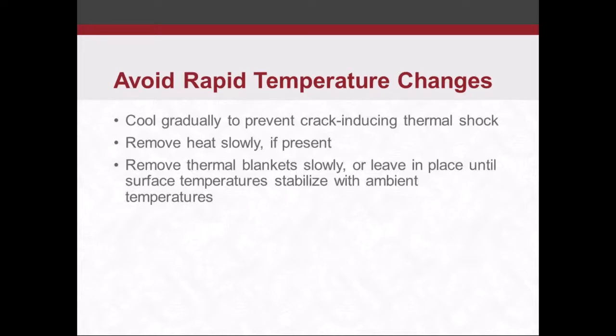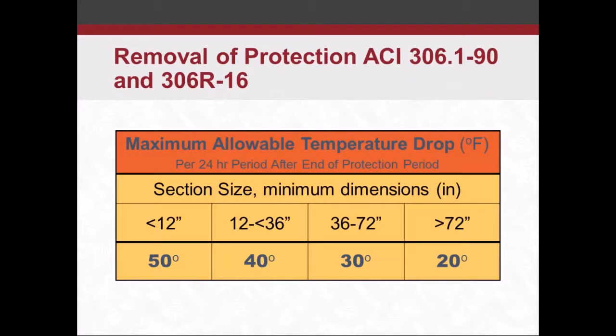But you want to make sure that you're avoiding rapid temperature changes. This table here identifies what the allowable temperature drop is in a 24-hour period after the end of the protection period. So we've already protected it for our 3, 4, 6 days or whatever that requirement is. Again, going by minimum section size, if our sections are less than 12 inches, again, this is our 8-inch, 10-inch, 12-inch walls, we don't want to have more than a 50-degree temperature drop in a 24-hour period of time.